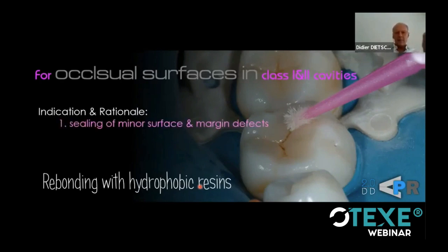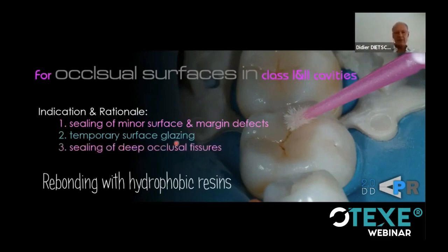What is the rationale of rebonding? Rebonding means that we want to seal the minor surface and margin defects, which always exist. Even if we don't see them, after finishing, just doing the restoration, there are always micro defects at the margins. And also as a temporary surface glazing, because it's very difficult to sculpt deep the anatomy and then to polish it in a perfect way, because we don't have instruments to polish this. We should use pastes, but it's so much easier to glaze the surface for these posterior restorations. And also to seal the very, very thin, deepest part of those grooves.